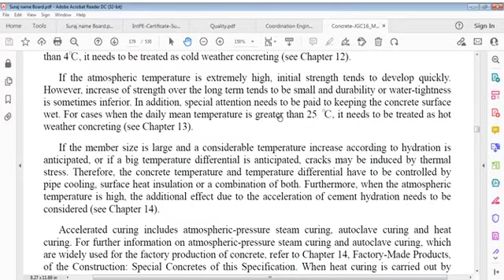When temperature is extremely high, initial strength tends to develop quickly. However, increase of strength over long term tends to be small, and durability or water tightness is sometimes inferior. In addition, special attention requires to be paid to keeping concrete surface wet. For cases when daily mean temperature is greater than 25 degrees Celsius, it requires to be treated as hot weather concrete. We'll see it later on.